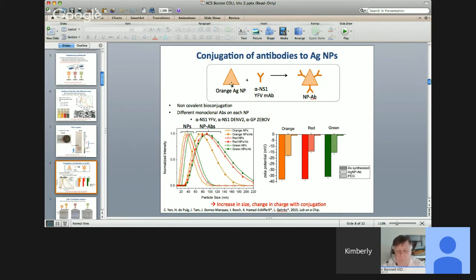So we take the orange nanoparticles, we conjugate them to the antibodies for yellow fever. The antibodies are specifically for a protein called NS1, and it's known that that's present in the bloodstream when you're infected with yellow fever. We take the red particles, we conjugate it to a different antibody for dengue. There's also a protein called NS1, but it's a different sequence that is specifically for dengue. And then we do it for Ebola. We take the green particles and we put antibodies for the viral glycoprotein on that surface, and that's the other bioconjugate.